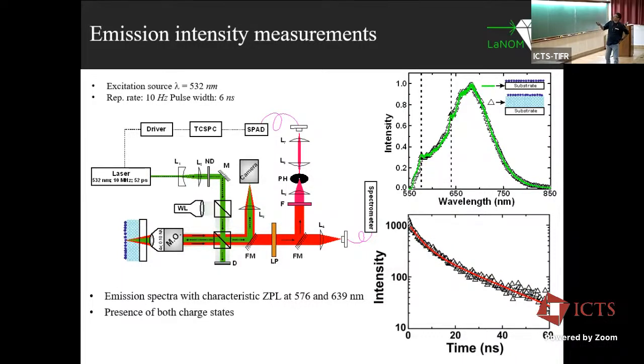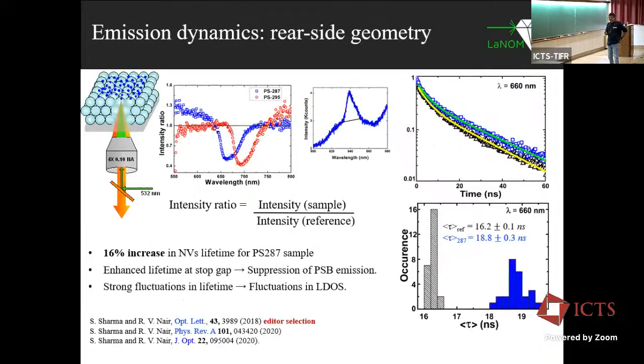For our reference photonic crystal with the NV center, you can see that the emission spectra does not show any change induced by the system, as expected, because this is a reference sample. And in the first experiment, where we excite the NV centers from the back of the photonic crystal, we collect the emitted light and plot the intensity ratio. You could see that there is a decrease in the emission intensity at wavelengths from 660 to around 700 nanometer. These are phonon contributions which are suppressed due to the band gap effect.